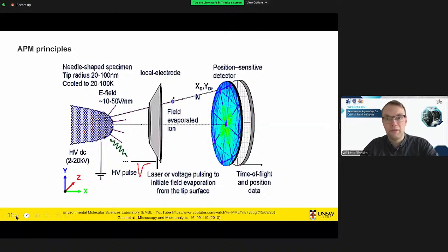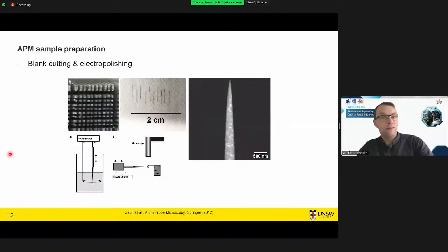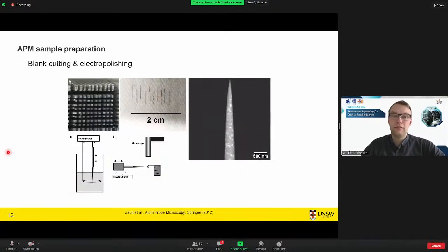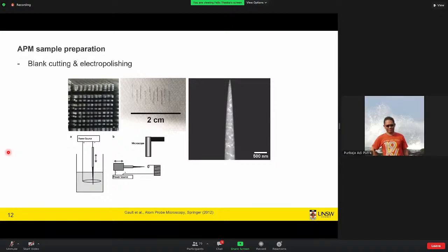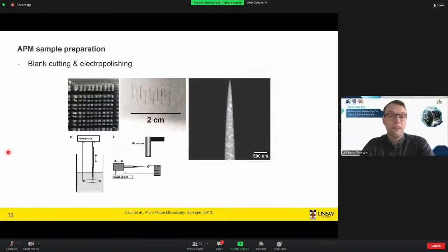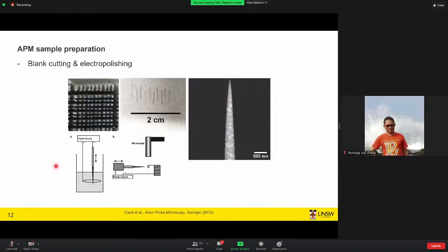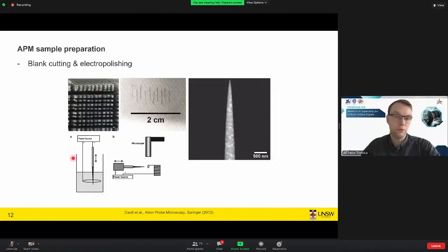Okay, so this is just a sketch of what we have just seen, in case the animation wouldn't work. How we get these very sharp needle samples is quite well established. For example, for these bulk samples, we would start slicing them and then cutting them into smaller rods, as you can see on the left-hand side, and then electropolishing them, such as on the bottom side. That's done with these rods placed through a micro loop with an electrolyte. And if we electropolish long enough, they will approach a tip shape, which is indeed very sharp, as you can see in this SEM image.